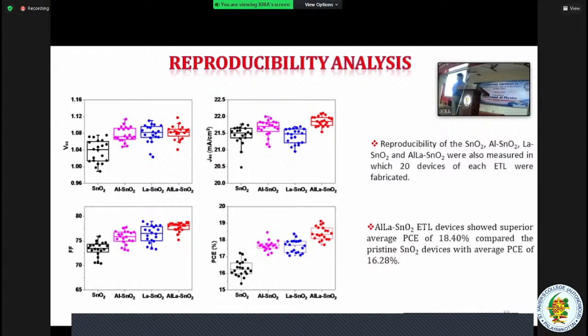So this is the reproducibility analysis. We have not done it only with a single sample. We have prepared 20 perovskite solar cells in each category: pure tin oxide, aluminum tin oxide and lanthanum tin oxide. So 20 devices we have checked for VOC, JSC, fill factor and PCE. From this we can clearly say that for the aluminum lanthanum doped tin oxide ETL, the average PCE value is 18.4%, whereas for the tin oxide, the average PCE value is 16.28. Next slide.